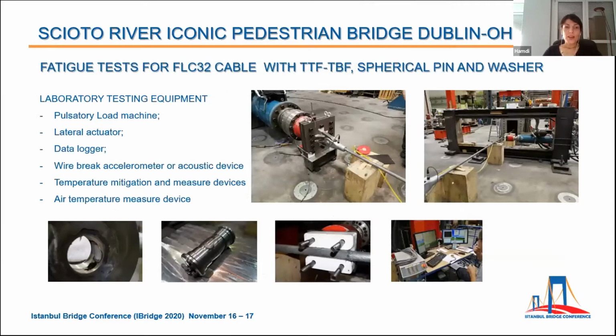The structure under the live load has significant movement, and this movement changes the overall geometry of the bridge. In order to simulate the cable during the service life and to understand their behavior in such high and eccentric fatigue loading circumstances, axial and bending fatigue test was carried out on FLC 120 and FLC 32 cables. Here you see the test on FLC 32 cable. This test was done on a specimen with a permanent socket in Kipcon laboratory in the Ruhr University of Bochum, Germany, with horizontal pulling machine.